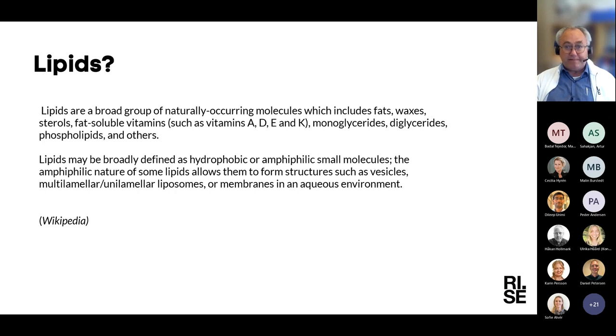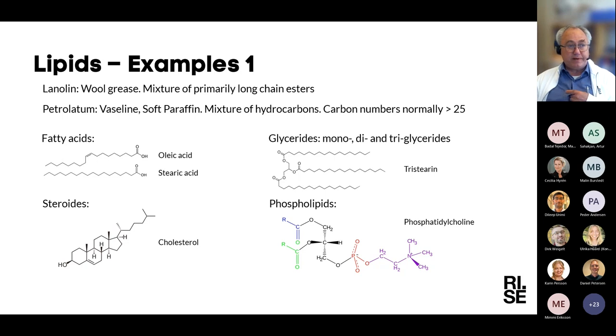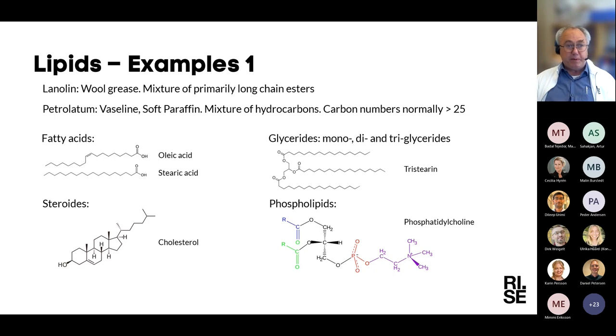Lipids have been around in pharmaceutical applications for at least 2,000 years — there's nothing new. Some of the older and more common lipids include lanolin or wool grease, which is a mixture of primary long-chain esters; and petrolatum, also called vaseline or soft paraffin, which is a byproduct from the petrochemical industry and a mixture of hydrocarbons normally with more than 25 carbons.